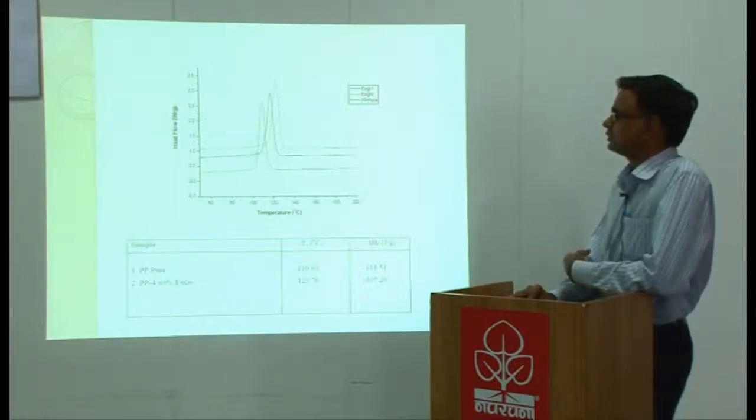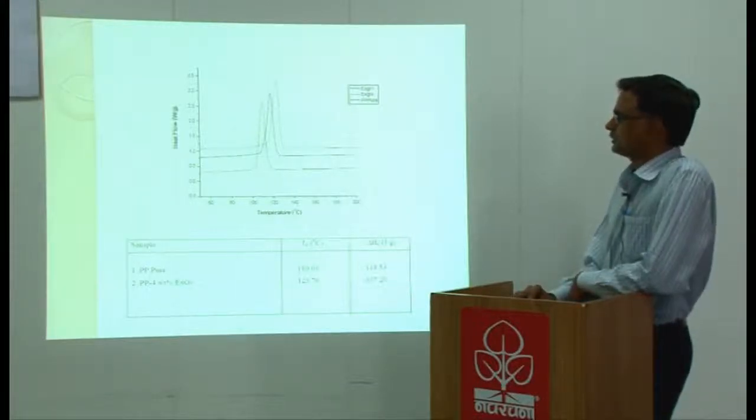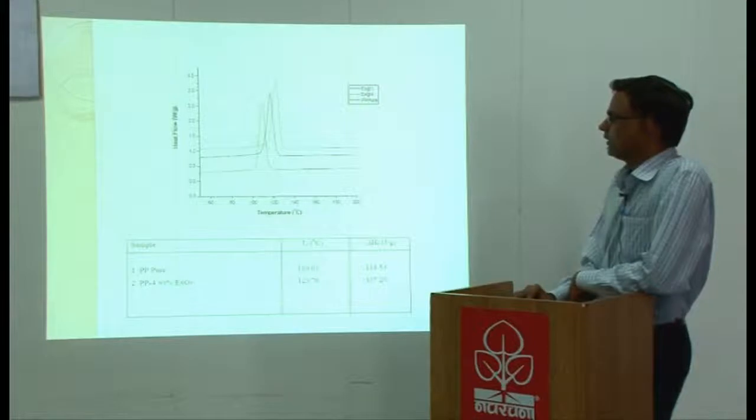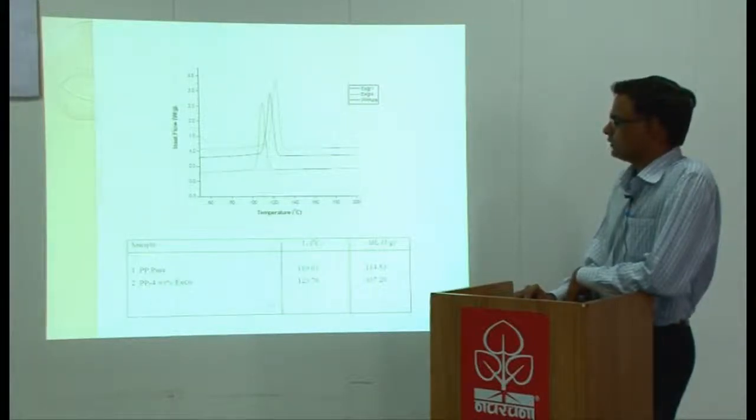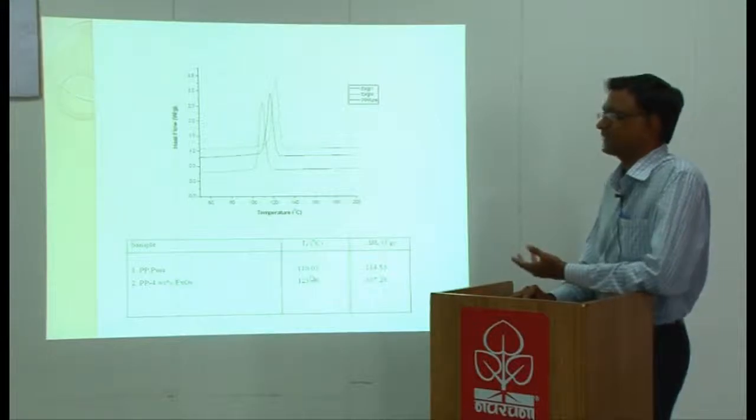Here you can see in PP when I add 4 weight percent of expanded graphite, the crystallization temperature is almost like 13 to 14 degree enhancement in crystallization temperature could be realized.